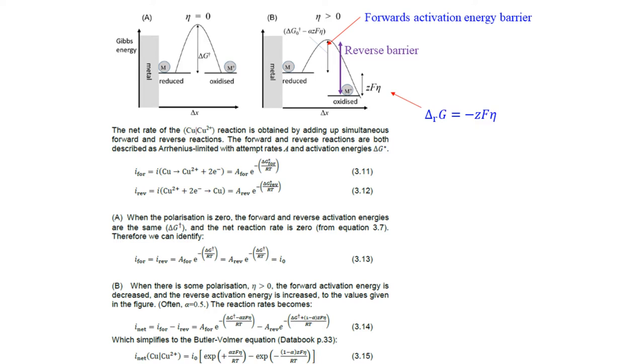Algebraically, we say that of the total energy drop ZF eta, the forwards energy barrier decreases by some fraction alpha of that, so that the forwards activation energy becomes delta G dagger minus alpha lots of ZF eta. Often alpha is 0.5 in simple cases. And likewise, the reverse energy barrier is increased by some amount. If we put those new energy barriers into the forwards and backwards reaction rates of equations 3.11 and 3.12, then we get equation 3.14, which tells us that the net current density is now the forwards current density minus the backwards current density. And if we put terms in and simplify using equation 3.13, we get an expression for the net current density of our copper to copper 2+ electrode. This equation is 3.15.